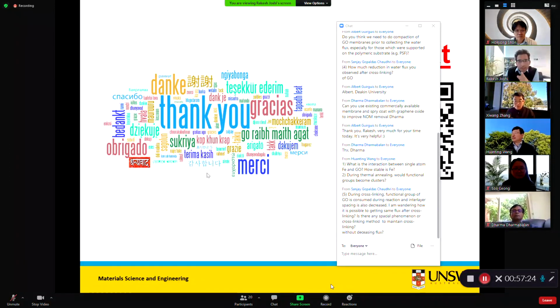Question: analyzing whether functional groups become clustered? Yes, that is the work. In Nature Chemistry, Hongwei's group showed that when you do a controlled annealing, the functional groups don't go away from the graphene oxide, but they make self-clustering, so they move closer. That's what we did in our TEM study. Our NMR study shows that the concentration of groups doesn't change, but the graphitic area is larger, which shows they make clusters. We call it self-clustering, and in our arXiv paper we have all the results. That was our aim: to make self-clusters that make graphene oxide stable, and the graphitic domains will have a larger flux.